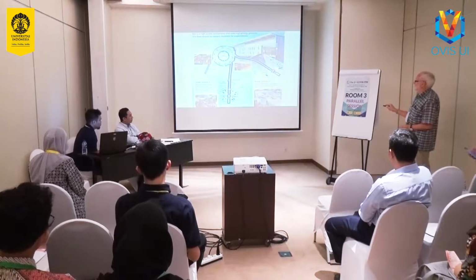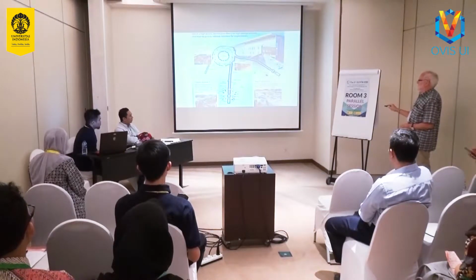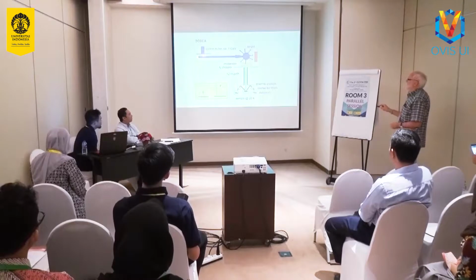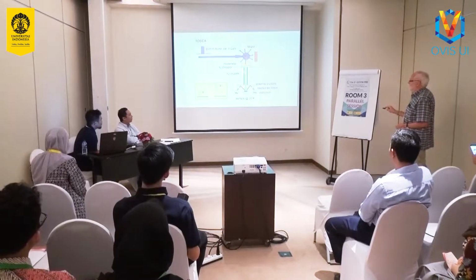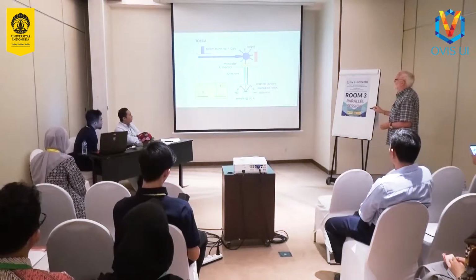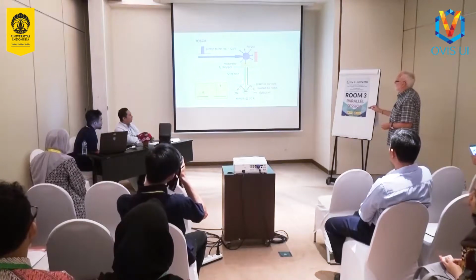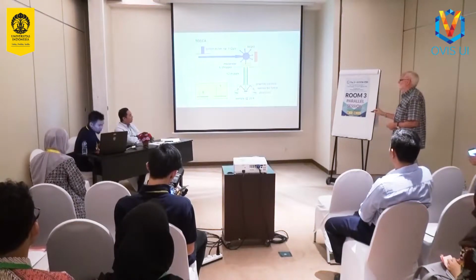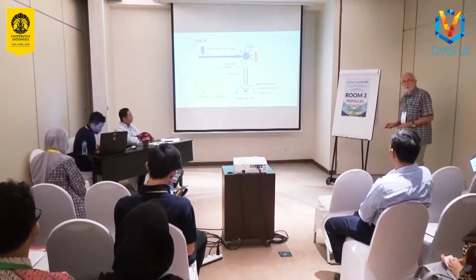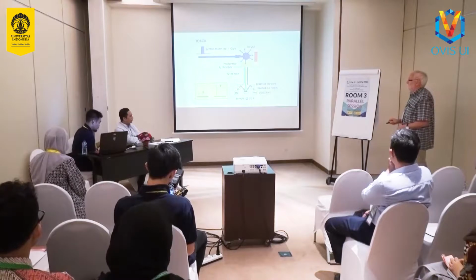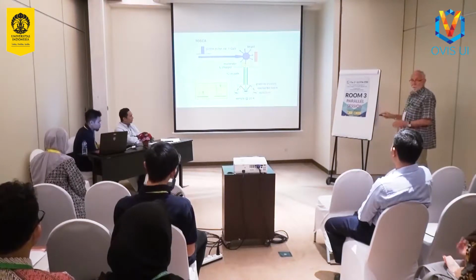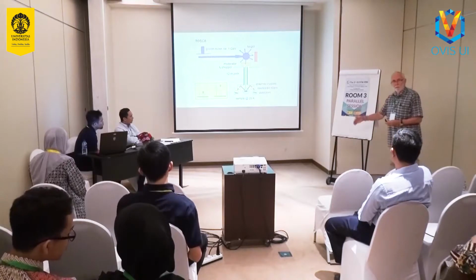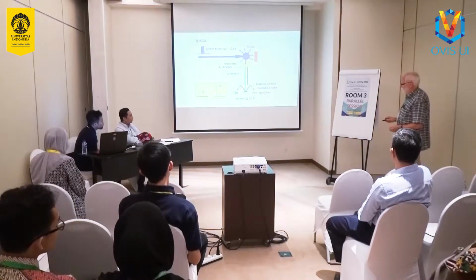There's another beamline here which produces low energy neutrons for other sorts of experiments. But basically, I go to the next one, I think it explains that a little bit more schematically. We have a proton pulse which strikes a target, generates neutrons, and then we have a spectrometer which can analyze them. Here's the sample, neutrons hit the sample, we measure the energies and the directions and the momentum of the scattered neutrons. The sample is held at usually 20 Kelvin or even lower for maximum sensitivity. Because the protons are in a pulse, the neutrons come out in a pulse. So the repetition rate is a few hertz. So we're getting pulses of neutrons hitting the sample and then being scattered. And we want to collect them and measure their energies.